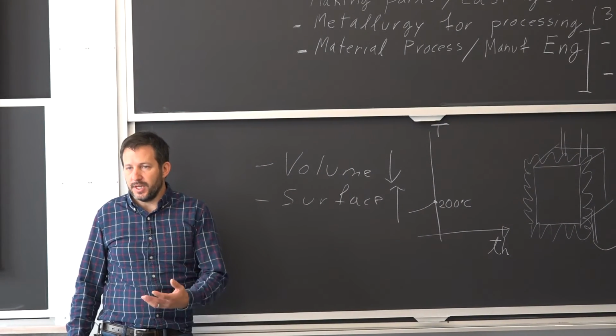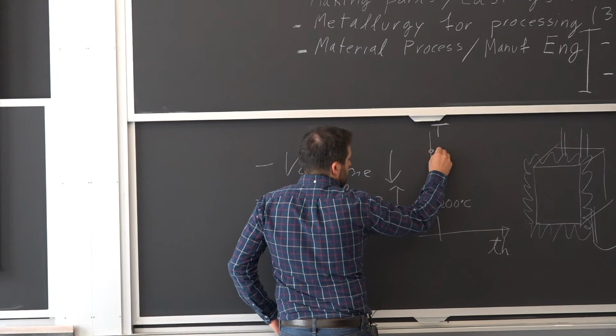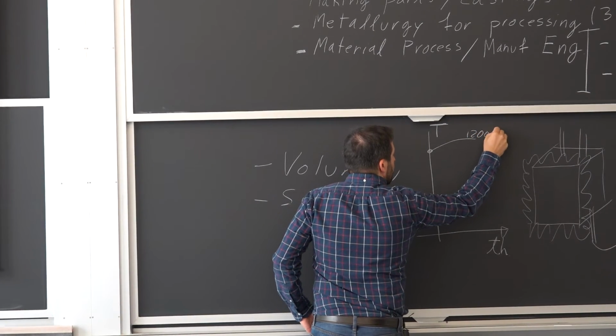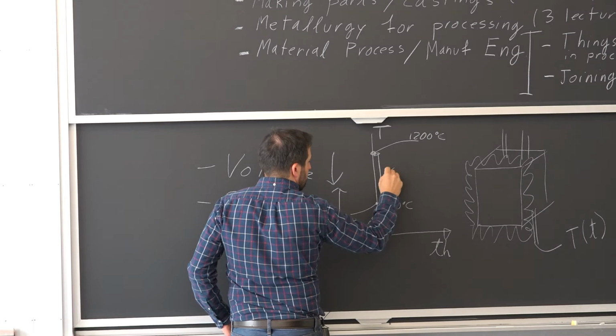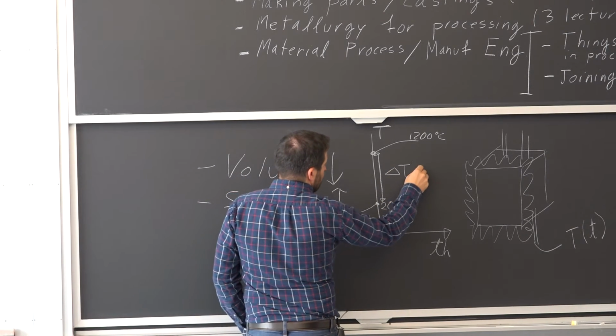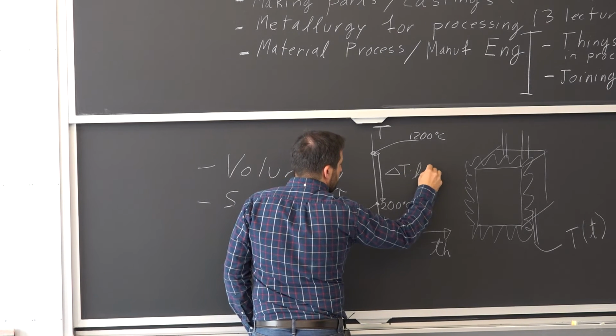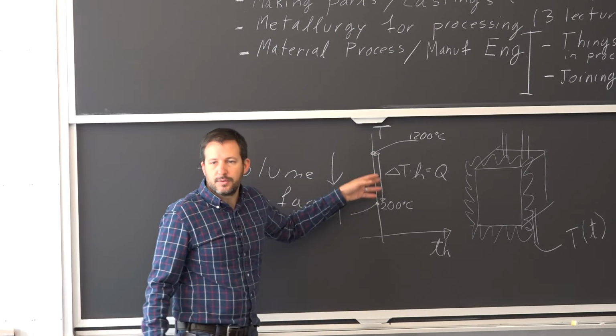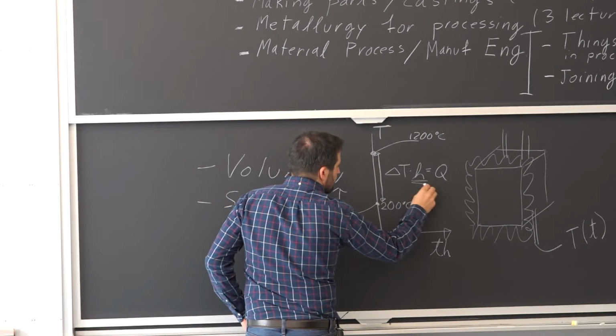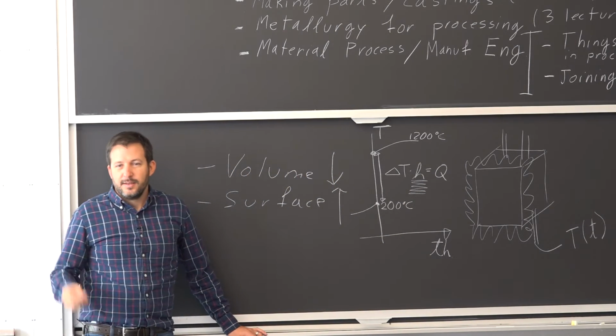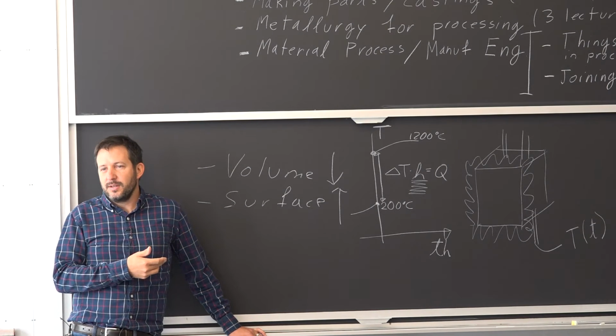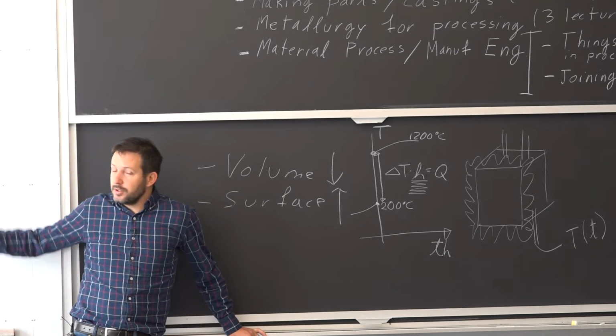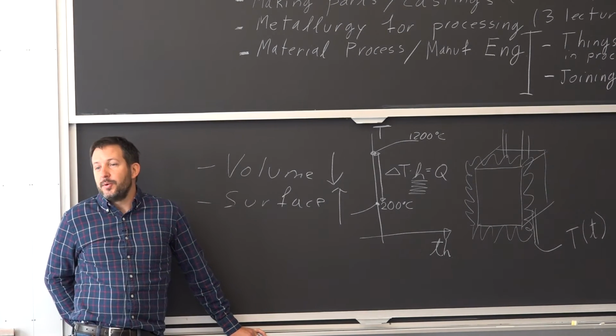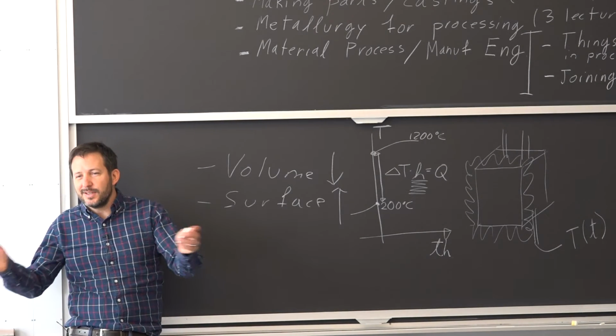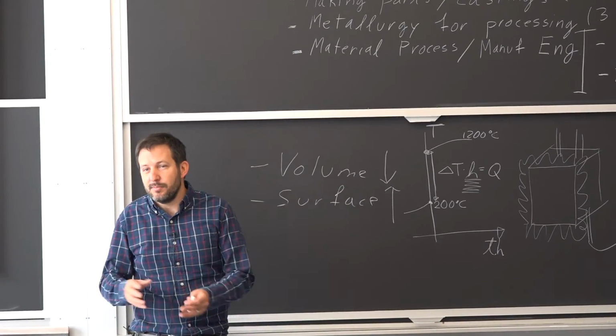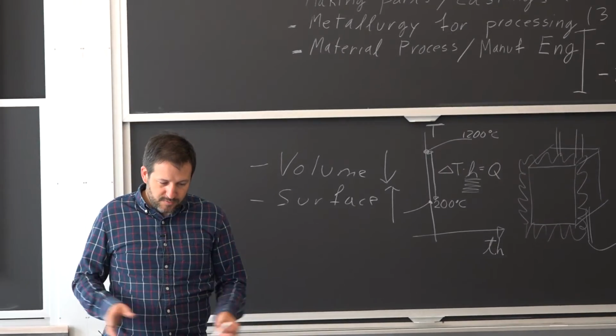That's the reason for this slide. I want you guys to understand that you have the liquid metal on the other side, that's 1200, and you have that big gap here, delta T, and then if you combine that with a certain constant, that's your heat transfer coefficient, it gives you the energy transfer across the mold interface. So the significance of this parameter for processing is money. If I can transfer the heat more quickly and safely and with a good quality product, I want to do that. I don't, because even our die casting that I've showed you, you see it's closing. It takes a couple minutes. It's not like a press that makes little nuts and bolts very, very quickly.